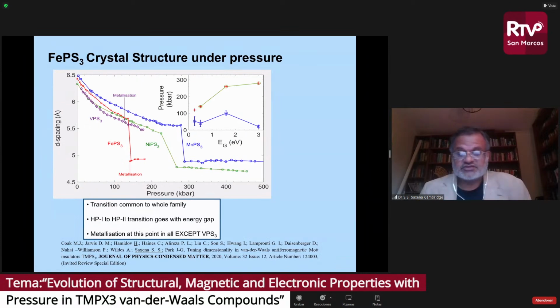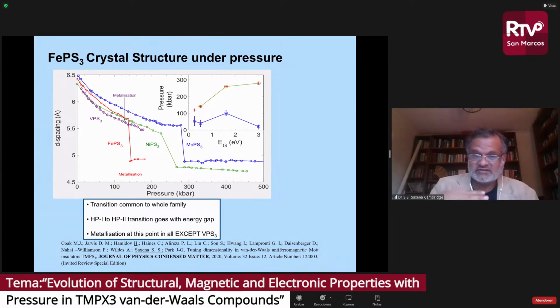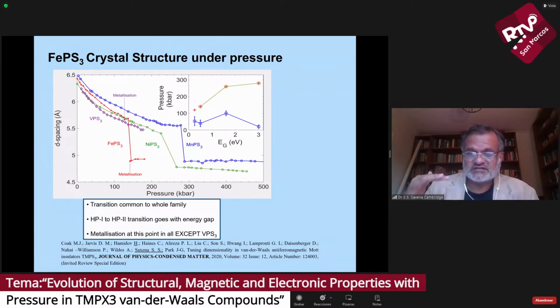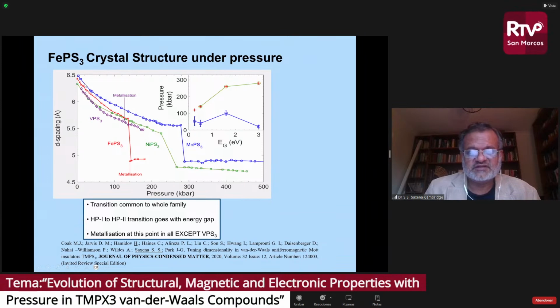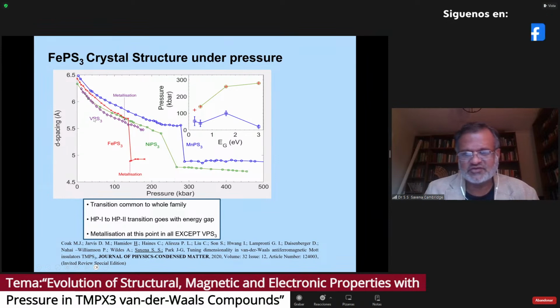Then we carried out similar structural studies on the full family. For the sake of time, I can't show you all of the data, so I'm showing you just the highlights. The key thing you see here is that all of these materials have a similar trend. They metallize when we see the c-axis collapse happen, except in the case of VPS3, and I don't have time to go into that.